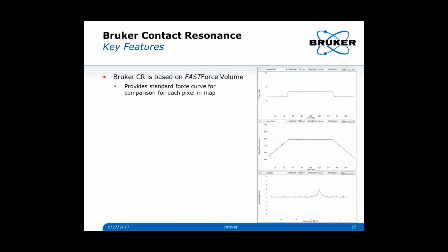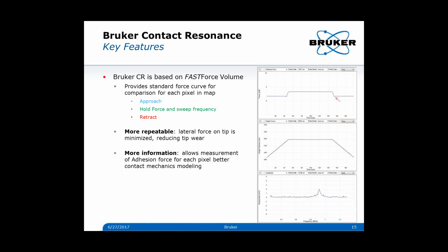So it's based on fast force volume. We do a hold, and that's represented here. We first approach the sample, then we hold, and we do a sweep during that hold on the ultrasonic actuator, and then we retract. And so we get essentially no contact during the lateral tip move, so we reduce tip wear from that.